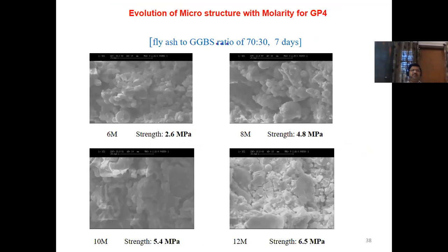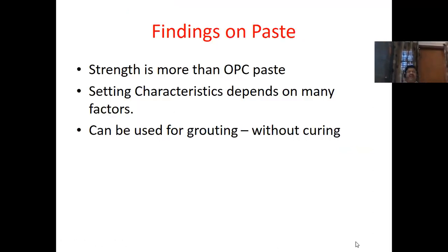And if you see the molarity, so it is 6 molar, this is 8 molar, 10 molar, and 12 molar. That means this is the amount of sodium salts added to a particular solution. So that is called molarity. It is for 6, 8, 10, and 12. So for 6 molar, it is 2.6. For 8 molar, it is 4.8. 10 molar, it is 5.4. And 12 molar, it is 6.5. That means there is steady increase in strength with the molarity, right, at the given age. Next, what are the findings of the phase that we got?